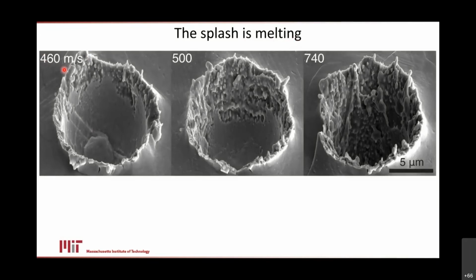And now look at the ex situ evidence here. These structures, they're rounded, right? This is molten tin that melted and it re-solidified in what is clearly a solidification structure all the way around the rim. So this is a melting related phenomenon. And as we go to higher velocities, we see that it's not just around the rim, but it penetrates deeper and eventually all the way in at high enough velocities. So extensive surface melting where the particle has impacted the tin substrate.